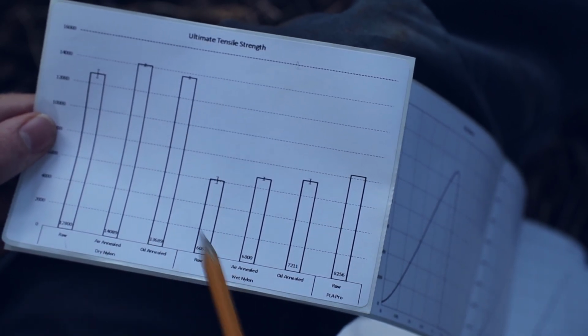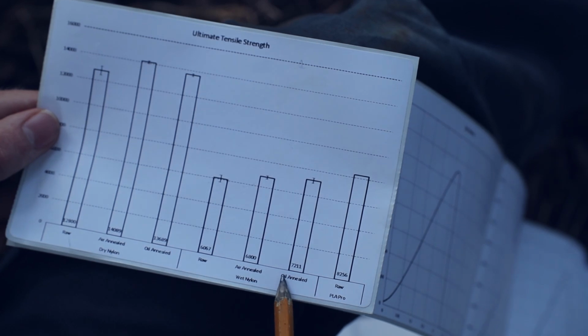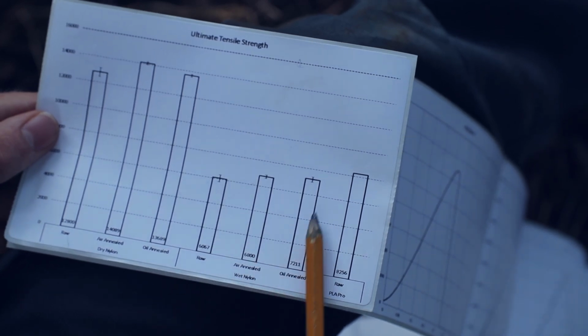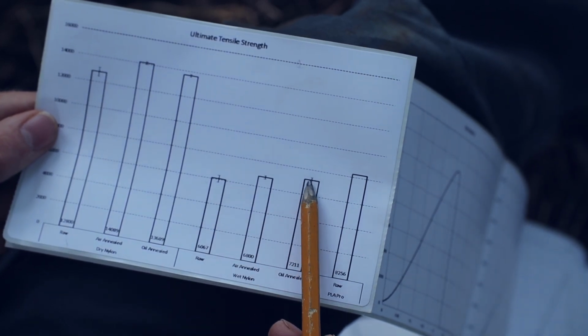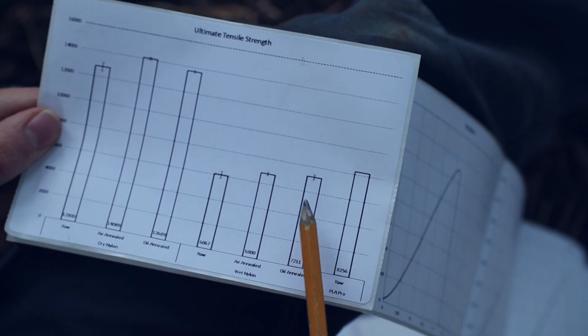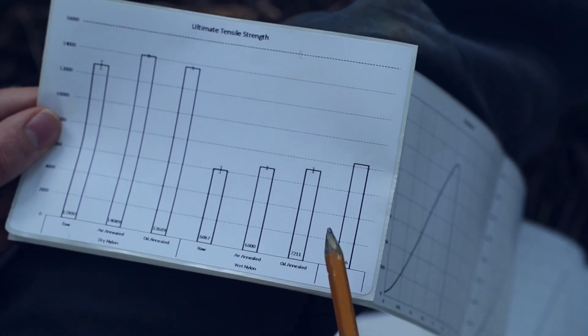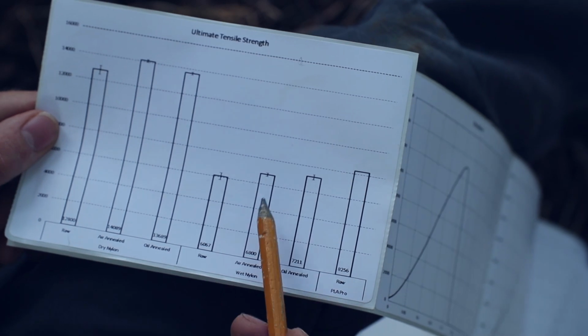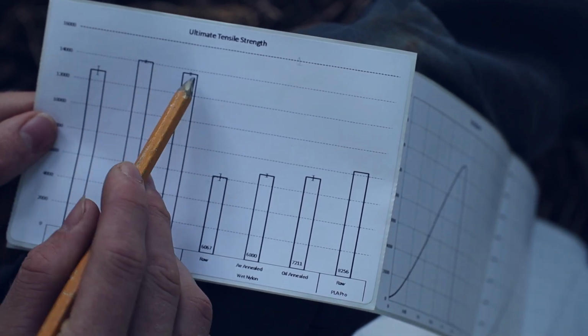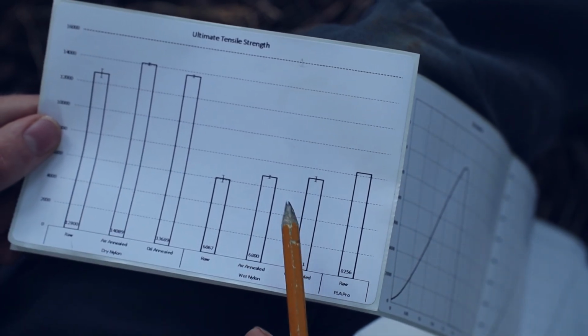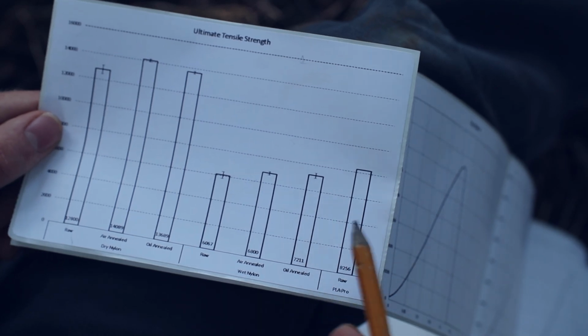When the nylon has been conditioned for 2 weeks in the atmosphere, the oil annealing is now the strongest of the three. The reason this is so critical is that my assumption that the oil was going to prevent moisture absorption is true. Even though the oil is not making the nylon stronger by itself, it is now stronger because it prevented the moisture from being absorbed by the nylon.